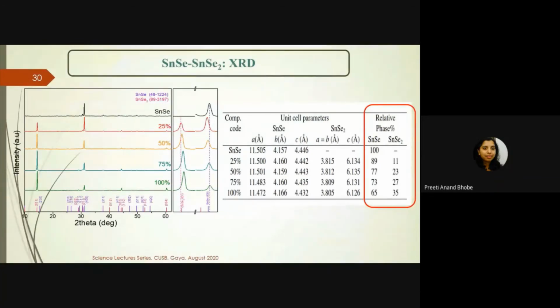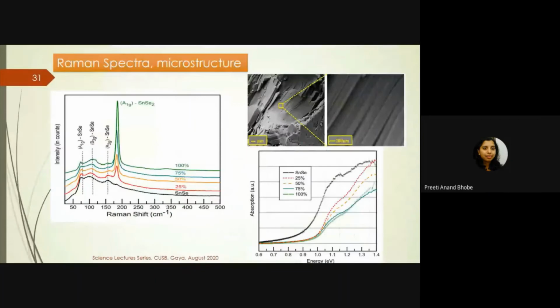Even for a 100% composition of SnSe2, we get some 35% of SnSe phase with a major portion of SnSe2 phase. With this, if I try and do the Raman spectra of this, there also I get that in pure SnSe there is no SnSe2 phase, but in pure SnSe2 there is a small amount of SnSe present. And if one tries to look at the microstructure, the layered microstructure has remained intact for all this material. That layered structure of SnSe, which actually makes it a better thermoelectric material, is still there. That does not get affected by this kind of change in stoichiometry. Optical gap, of course, gets changed. It's quite different.